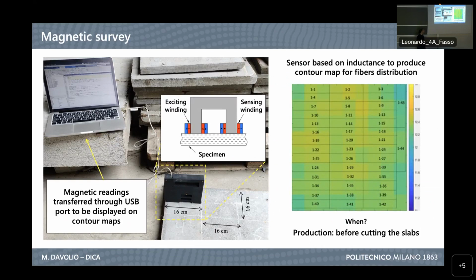This is the magnetic survey, and the purpose of doing this was to try to determine the distribution of the fiber, because of course when we cast fiber reinforced concrete, we don't know the actual result of the casting, especially when we discuss about on-site casting, which has some logistical issues. And for this purpose, we used this magnetic probe, which is able to measure the inductance of the material on a thin layer, which was perfectly suitable for our case, since we had nominally 30mm slabs. And from this, we could draw these contour maps.